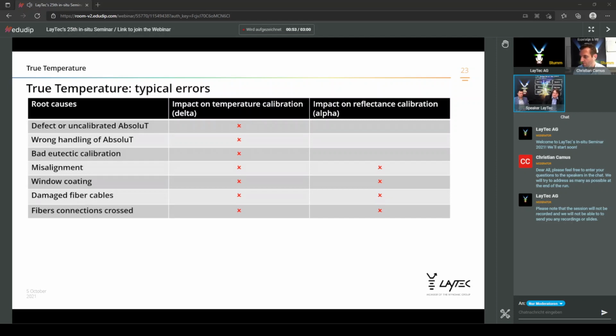What can also happen sometimes is that the fiber connections, typically at the fiber optical head of the AbsoluT, can accidentally be crossed. This can easily happen if you don't pay attention when you disconnect the fiber cables from the head, maybe for cleaning the reactor lid area or the glove box, or for repair work or leak tests. If you reconnect them and don't pay attention to the correct placing, you can easily cross the connections. Typically, the fiber cables are marked by clips right at the end where the connector connects to the fiber optical head. It indicates the fiber cables that feed the light from the light source, and the fiber cable that receives the light back to the controller, to the detector.